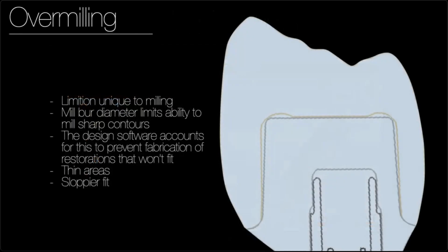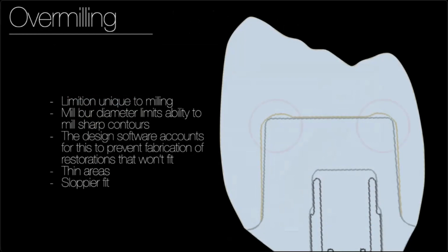One important concept to understand when milling is over milling. This limitation is unique to milling. What it is, is the mill burr diameter limits the ability to mill sharp contours. So you see here the angles of my abutment are sharp. And so what the program has done is it's over milled those areas so that when the restoration is made, it'll fully seat. What ends up happening though, not in this case, in other cases, is you can get thin areas in the ceramic, or you can get a sloppier fit of the restoration on the abutment.